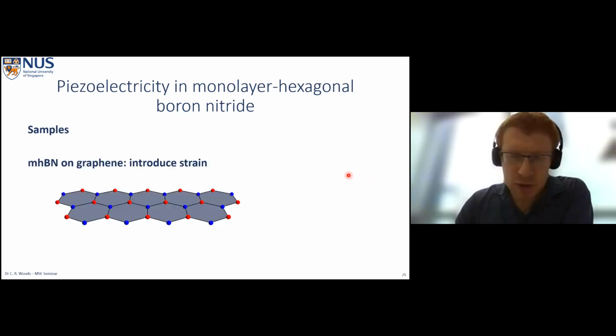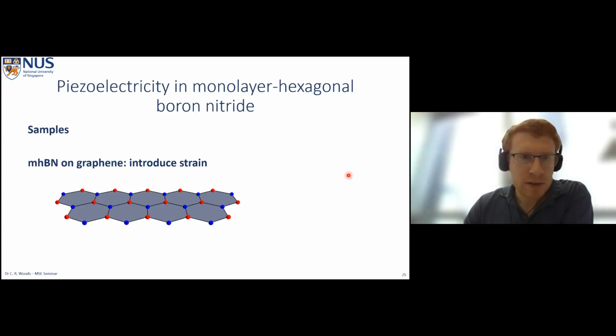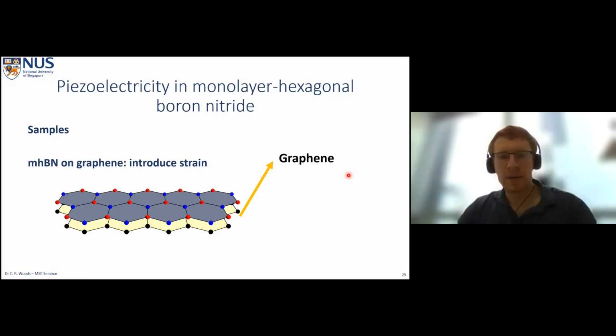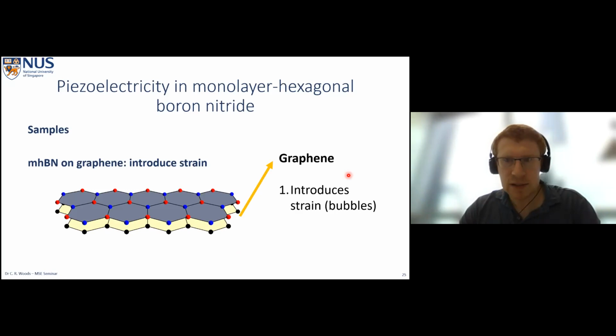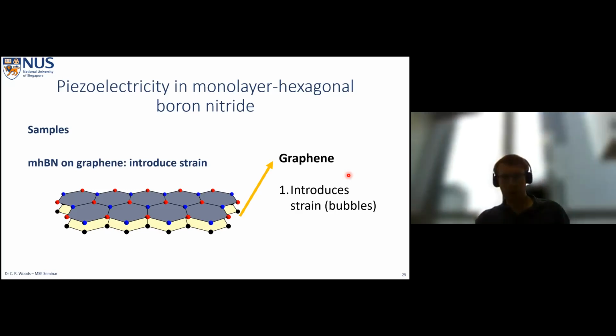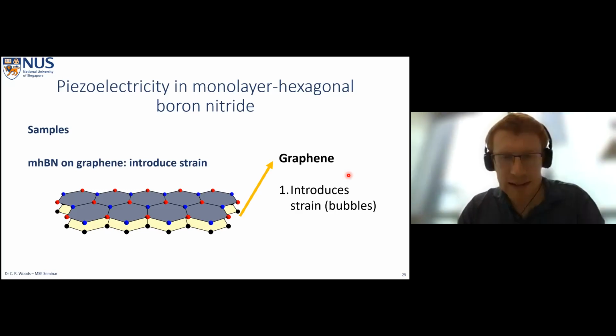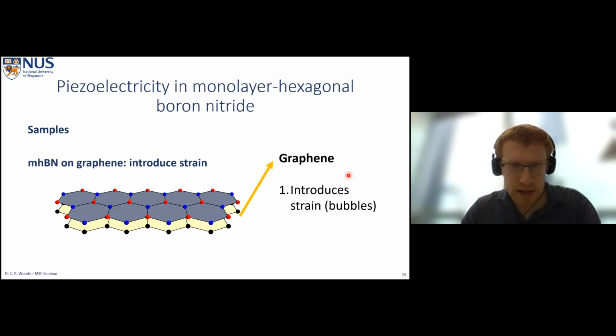Okay, so let's produce some samples to try and take advantage of these properties. So what we're going to do is we're going to take monolayer hexagonal boron nitride, and we're going to put it on top of graphene. Now we're going to use graphene for 2 reasons here. The first is that we can induce these contamination bubbles, which I'd discussed before. And these contamination bubbles are epicenters for strain. So they're going to be large strain producing features in our samples, and we can try and look at that and predict how the strain will appear not only on top of the bubble, but in the surrounding area too.